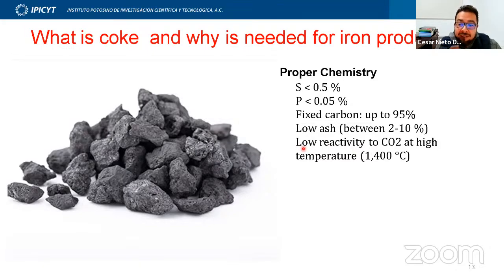And also, this is very important, it has to have a very low reactivity to CO2 at very high temperatures. As I showed you at the beginning, the cupola furnace or the blast furnace is just a shaft. At the bottom is the fuel, and at the top is all the material that is packed and heated by the heat made at the bottom of the furnace. You want this coke to survive all the way from the top of the furnace to the bottom. You want no reaction to happen as the coke travels from the top to the bottom. You only want reactions at the bottom where there is oxygen and you start combustion. Before that, you don't want anything.